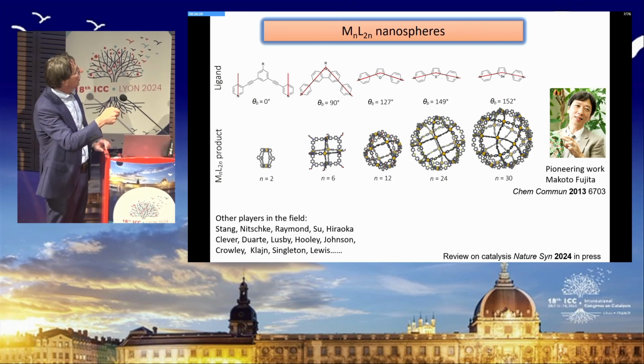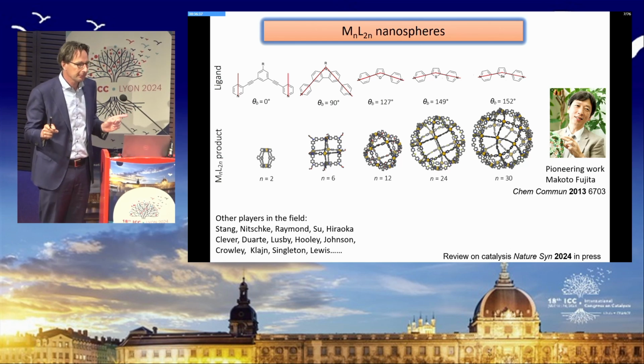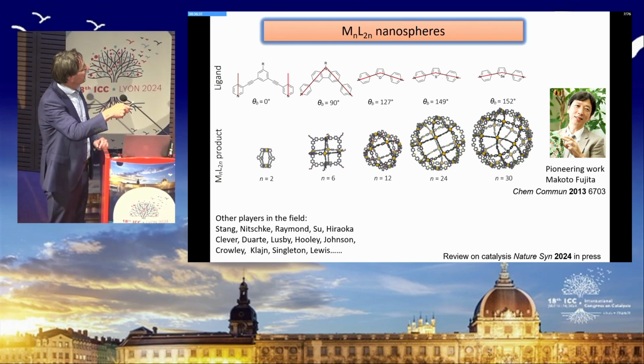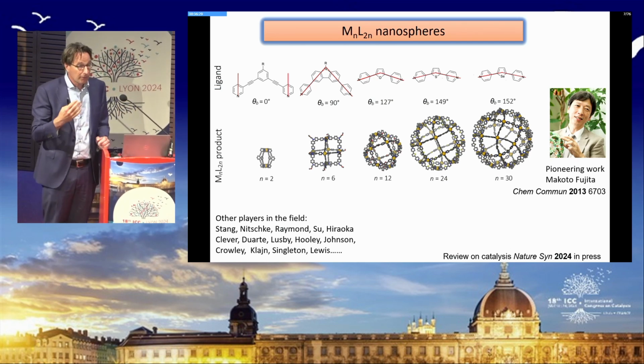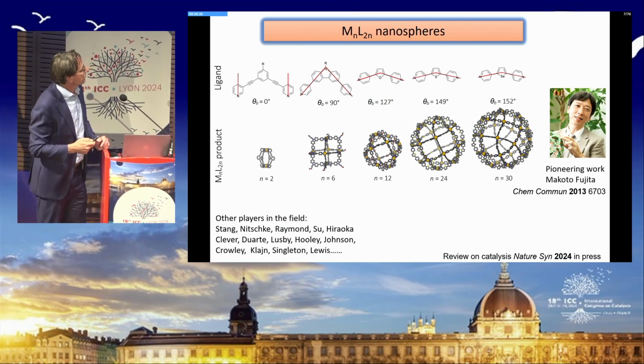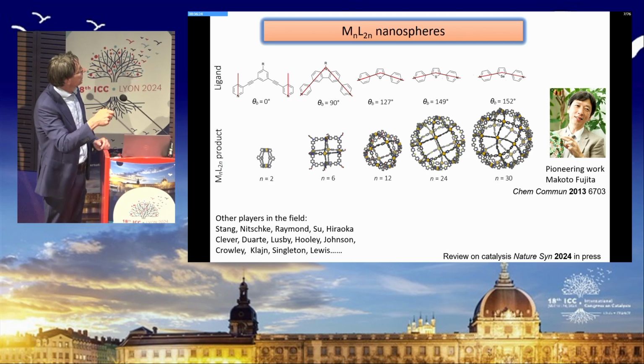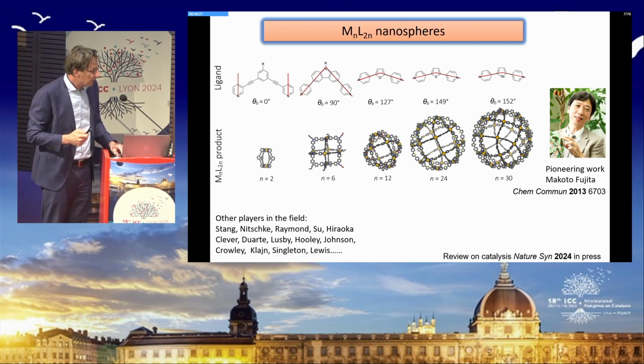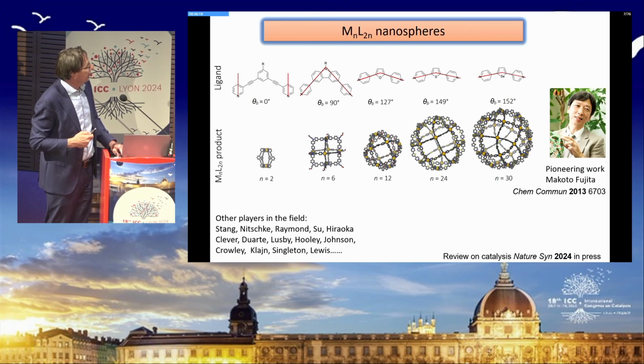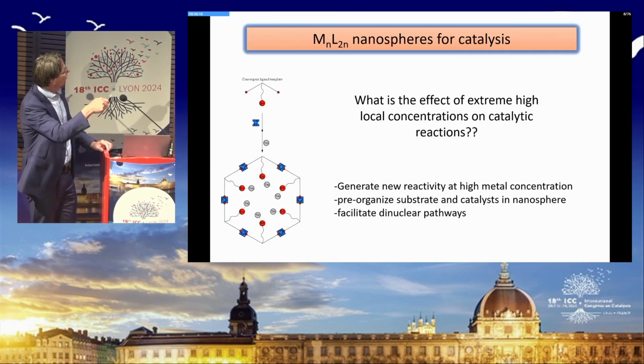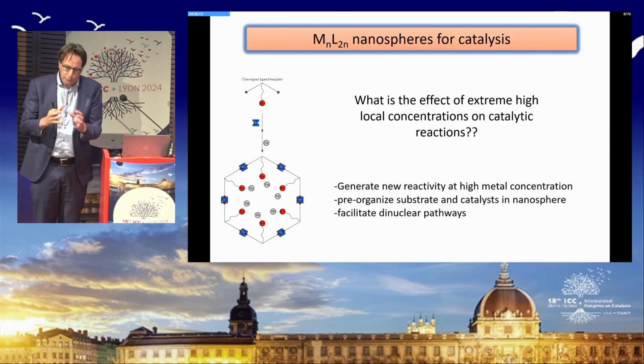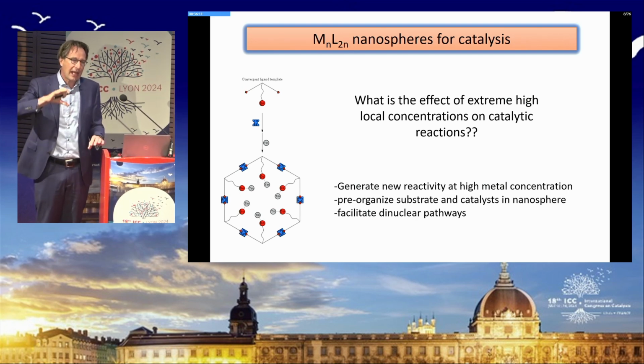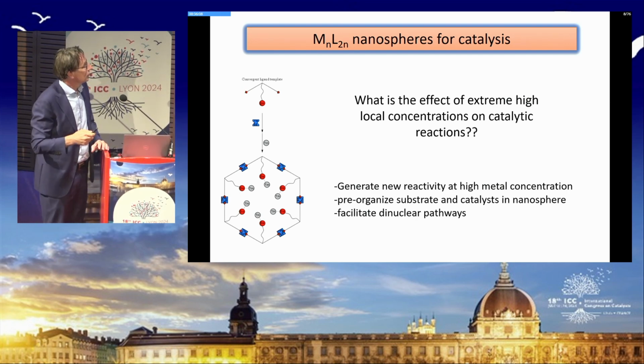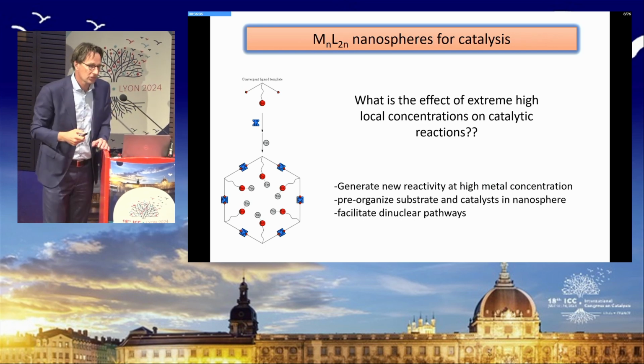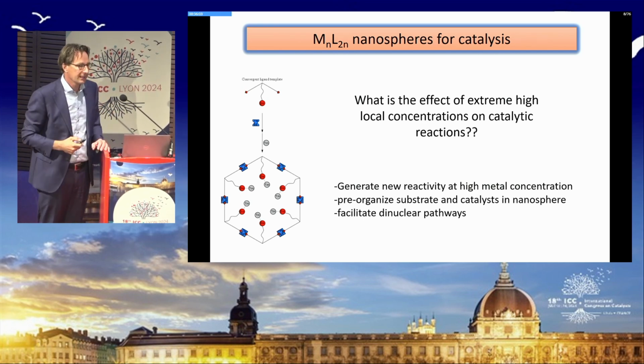And here you can see a few examples where you have ditopic pyridine building blocks, and if you add a palladium or a platinum precursor, you can form these nanocages in effectively quantitative yield. And here you just change the angle between these two. And we use these to functionalize them at the inside. And if you functionalize them at the inside, you can pre-organize metal complexes at the core of these nanostructures. So you get very high local concentrations of whatever you put inside.